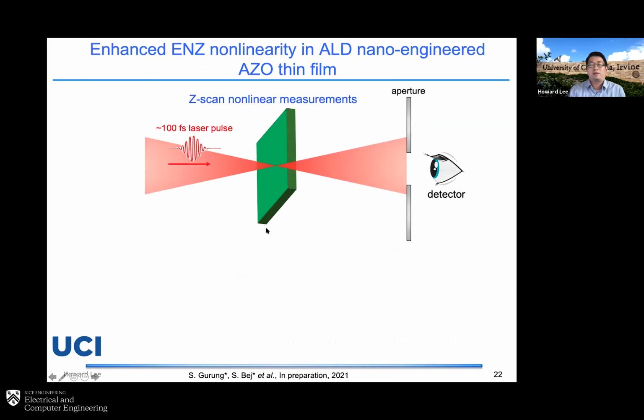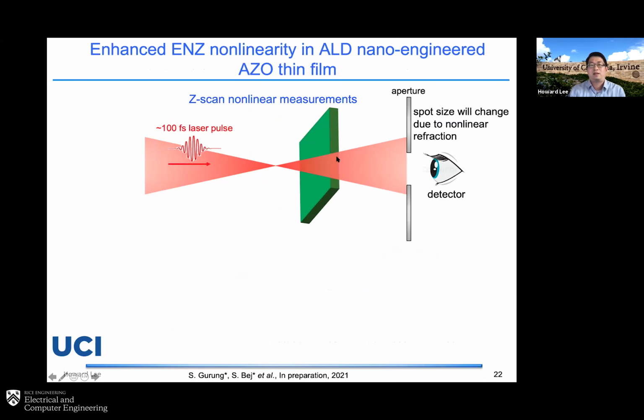So that's why we have been trying to work on that and trying to even further engineer this ENZ material to enhance the nonlinearity. And we're using the quite standard Z-scan measurement technique to measure the nonlinearity. I tried to simplify the setup here. Basically, you can imagine you have an ultrafast femtosecond laser with an ENZ material, and what you have is a detector and aperture here. By just scanning in the Z direction, you can change the intensity of the laser interacting with the material. As a result, you may see different nonlinear refractive index change, and as a result, you may see different spot size change here. So with this, you can correlate what kind of nonlinear effect you may have in this ENZ material by just a simple so-called Z-scan measurement here.